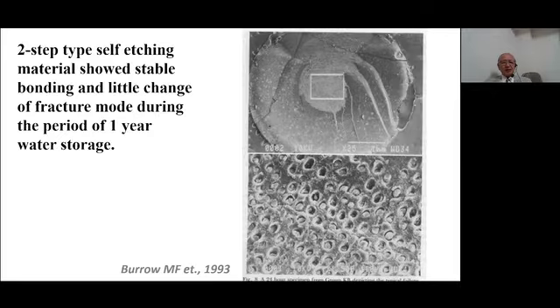When we preserve the specimen in water for 1 year, even after 1 year storage in water, the two-step type self-etching material shows stable bonding, and the fracture mode at the bond interface was still in the material, not at the interface, not at the hybrid layer.